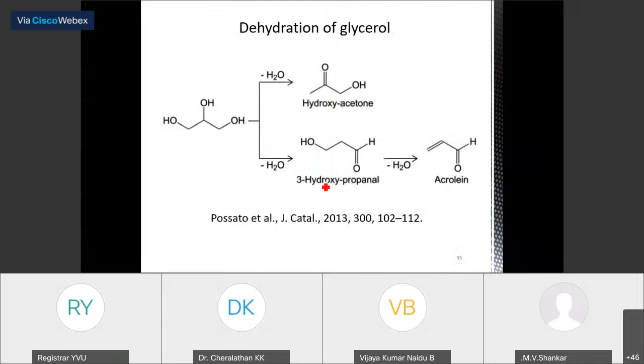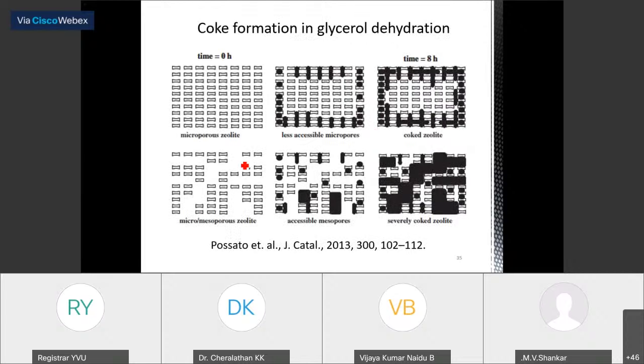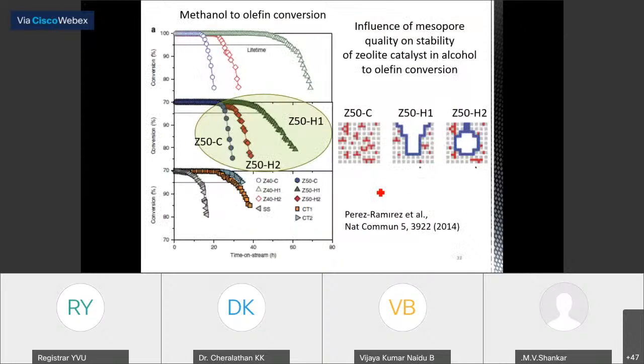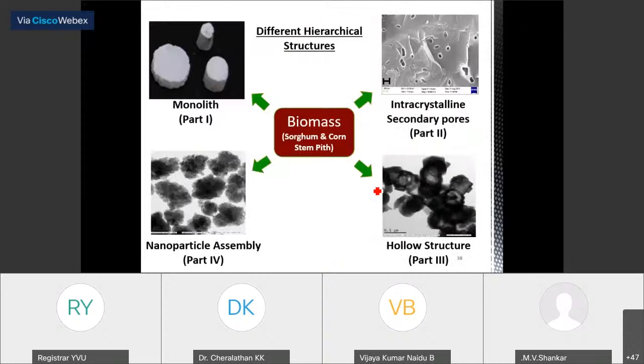Okay. So this will be reflected in other reactions also. For example, glycerol dehydration, acrolein and hydroxyacetone. People have studied this reaction and found out that when they have this kind of hierarchical pore structure instead of this kind of microporous pore structure, the catalyst stability is improved. Even though you have extensive coking after the reaction, the catalyst showed activity due to the presence of hierarchical pores. Like this, you can have a number of examples in the literature. From our group, we have done some work. One of the PhD students used agricultural waste to produce this kind of hierarchical zeolites. Okay.